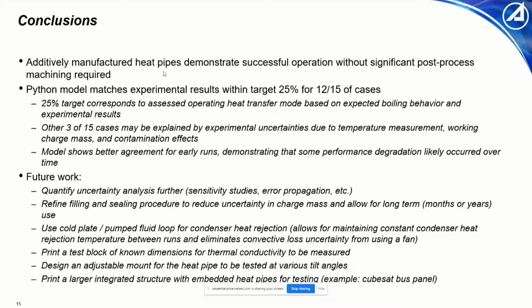It's important to note as well that the model does show a better agreement for early runs. 3 out of those 15 cases were from the very final run that was performed. And as you can see from the timeline that I showed previously, the performance degradation was certainly apparent. And because of that, we do conclude that the Python model is accurate in predicting the overall heat pipe performance.